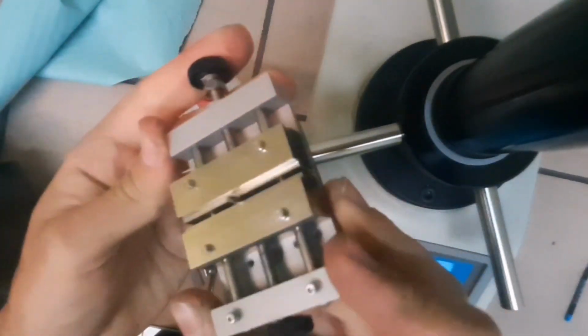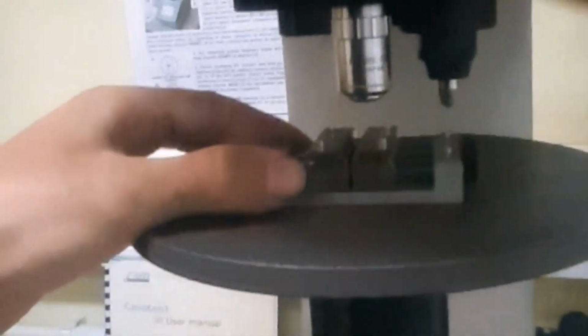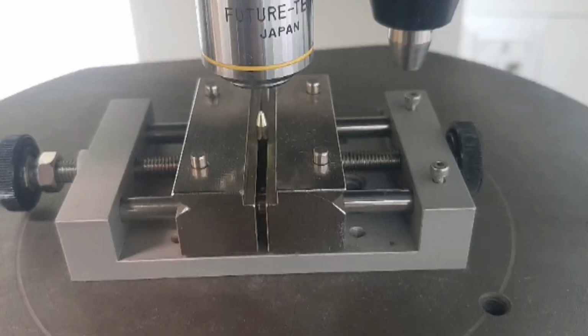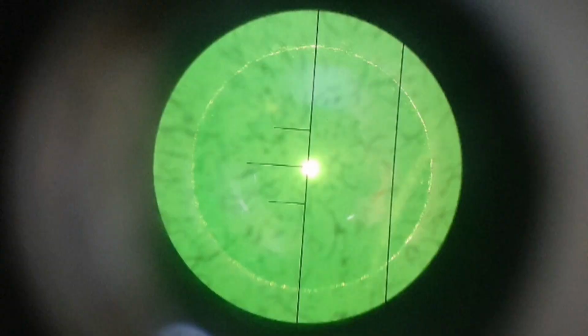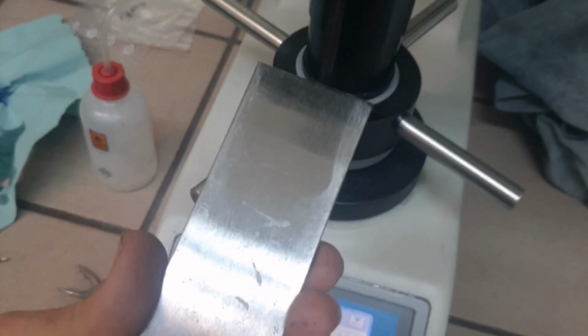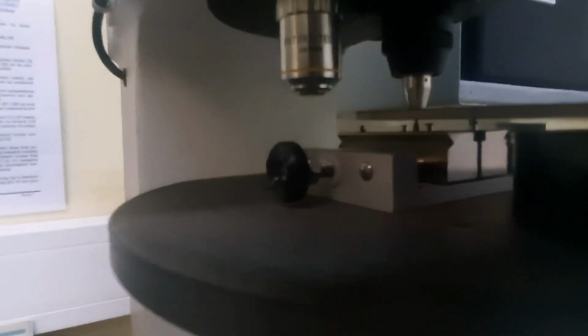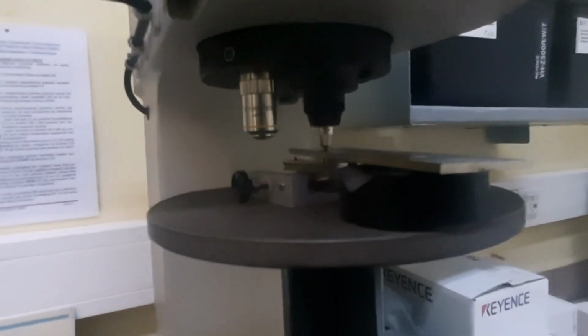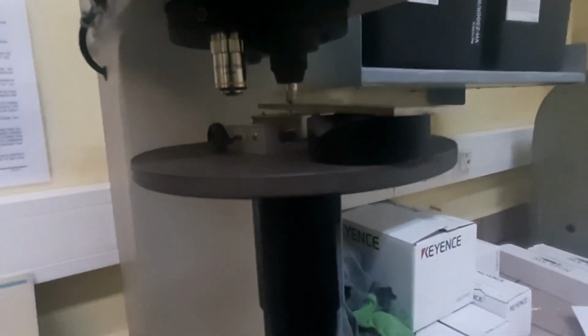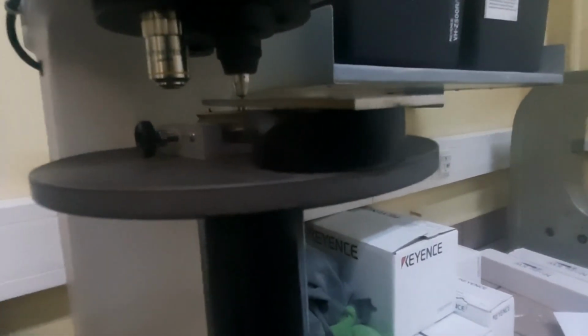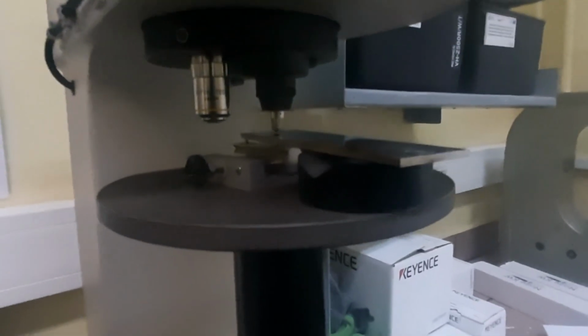That's why I will now remove the whole assembly of ball with a holder from the ballpoint pen, mounted in a vise, and then use the Vickers hardness testing machine to apply the load. I've placed the ball now exactly under the Vickers indenter, and I will put a piece of hardened steel between those two indenters, and now the weight is applied. From the top, the Vickers pyramid is being pushed into the steel, and from the low end, the Brinell ball is being pushed into the steel.